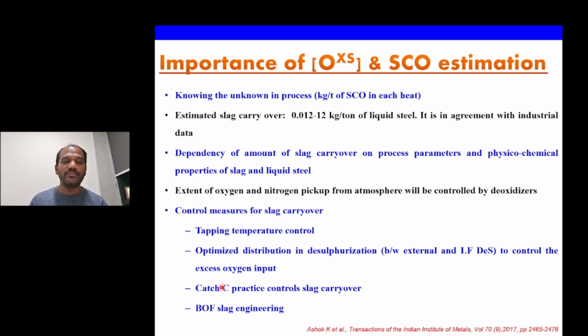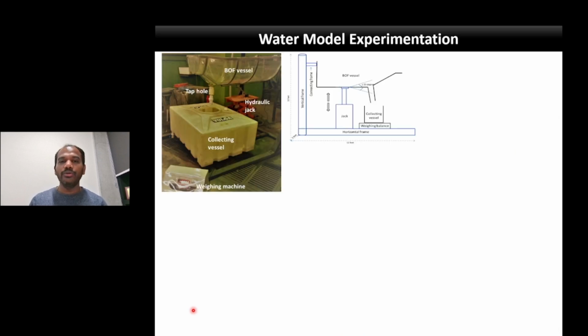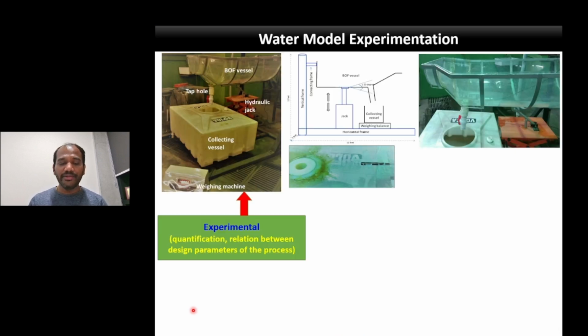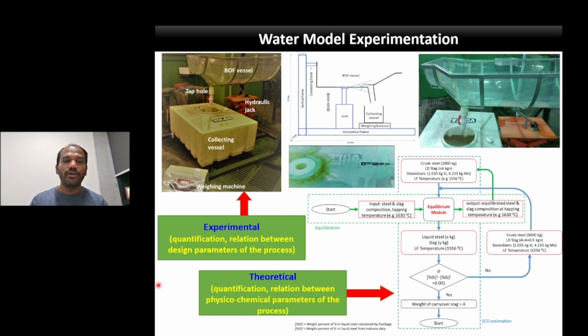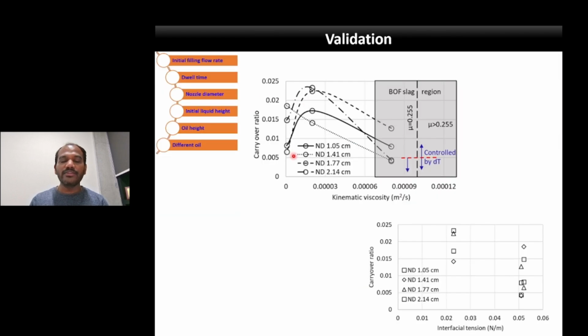So based on these investigations, we propose certain control measures for slag carryover: tapping temperature control, optimizing the distribution of desulphurization between external and LF desulphurization to control the excess oxygen input, and some catch carbon practice can be followed. BOF slag engineering can be done, and we wanted to validate this. So the water model experiments are planned. The schematic pictures of those models are given here, and the results are validated here.